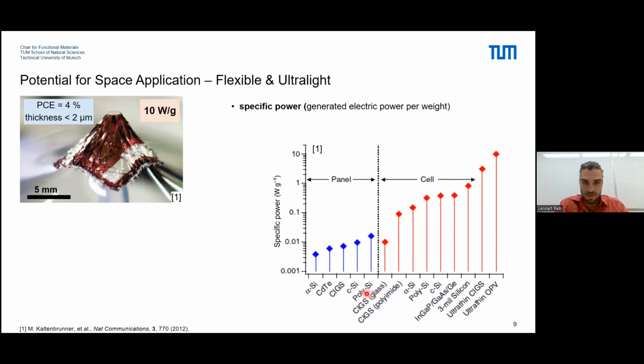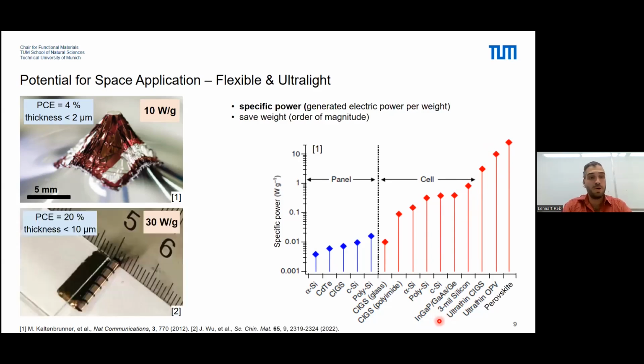And you can see here 4 different technologies. So here on the left, we have the panels, and here we have the cells. This ultra-thin organic photovoltaic device could reach a specific power of 10 watts per gram. This is a logarithmic scale. So this shows that there is a huge gap between this and the classically employed silicon or gallium arsenide-based technologies for space applications. In a more recent work, a perovskite solar cell with 20% efficiency and a thickness of still thinner than 10 microns achieved 30 watts per gram. And this value is added here. So what we have is basically an order of magnitude that we can save weight on the solar cell basis.